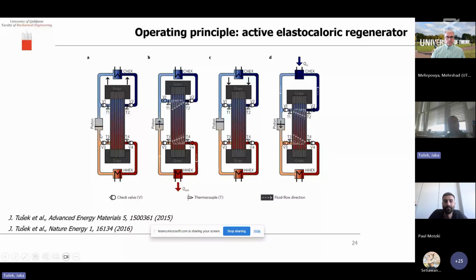Through this regenerator, the first step is loading, then the second step is pumping the fluid through these channels of this elastocaloric regenerator when the material is heated up, where the fluid is heated up and can then reject heat to the surroundings. The third step is unloading, so the material cools down due to the elastocaloric effect, and then we pump the fluid in the counterflow towards the cold heat exchanger, where this cold fluid is now able to absorb heat from the surroundings.